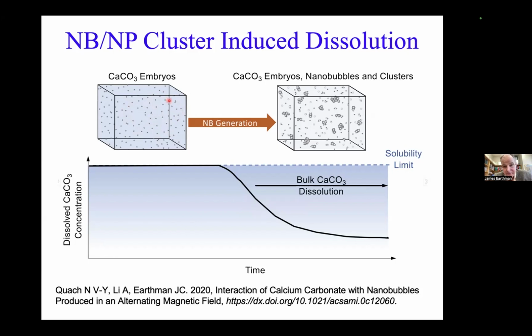pipes, when it's fouling. If you add nanobubbles, you're going to form clusters. Those clusters are going to stabilize these embryos over here, and they're going to keep them from dissolving back in solution. And you're going to force the concentration below the solubility limit. If you keep adding more and more nanobubbles to this, the concentration won't be able to catch up. You can keep it down, and you can keep dissolving the fouling solid that you've got in the system by just adding more and more nanobubbles this way.